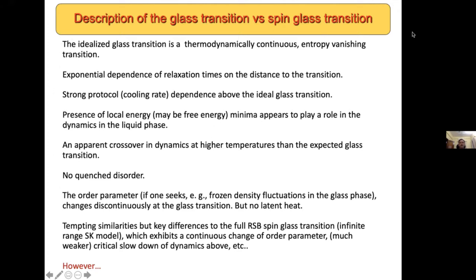Now, if one were to summarize what one can say in broad terms about the glass transition, here are the following things. The idealized glass transition, not the laboratory glass transition, is a thermodynamically continuous entropy vanishing transition. One has an exponential dependence of relaxation times on the distance to the transition. You have strong protocol dependence above the ideal glass transition. One has the expectation that the presence of local energy or free energy minima plays an important role in the dynamics of the liquid phase. And there is an apparent crossover in dynamics at higher temperatures than the expected glass transition, as described by the mode coupling theory. There is no quenched disorder.